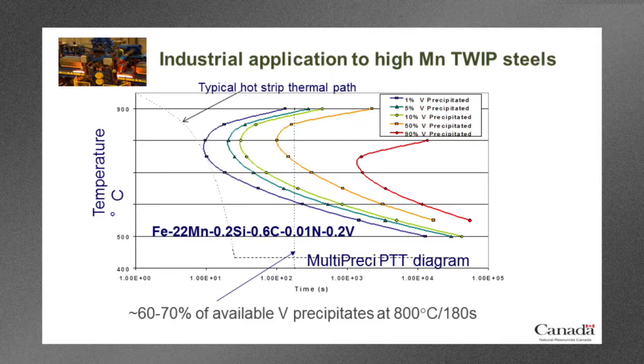The one on the left-hand side would be the typical cooling curve for a hot strip after hot rolling, where it would be coiled at between 400 and 500 degrees C. And the other one would be the temperature and the time that we would consider using in an annealing step after cold rolling. So it would be recrystallization annealing, which would be around 800 degrees C, maybe between 800 and 850 degrees C, for less than 200 seconds.